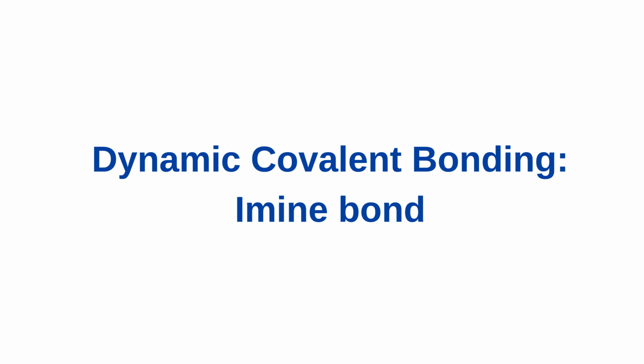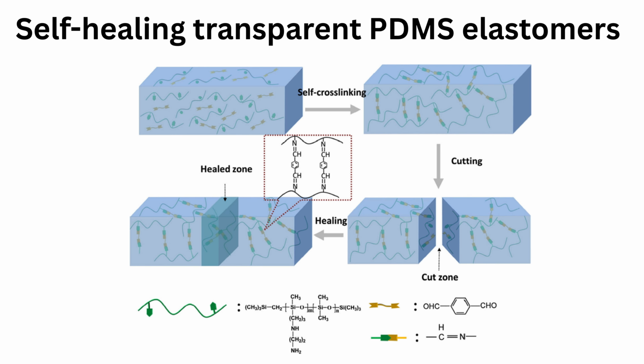Imine bond. The imine bond is defined as a dynamic, reversible covalent bond formed by the condensation of an amino group with an aldehyde group, resulting in the formation of a carbon-nitrogen double bond. This bond exhibits dynamic properties associated with self-healing and reprocessability without the need for external stimuli. Consequently, materials based on reversible imine bonds have garnered significant interest from the scientific community. Scientists successfully prepared healing transparent PDMS elastomers based on imine bonding using amino-modified polydimethylsiloxane, PDMS, and 1,4-diformylbenzene, DFB, as the